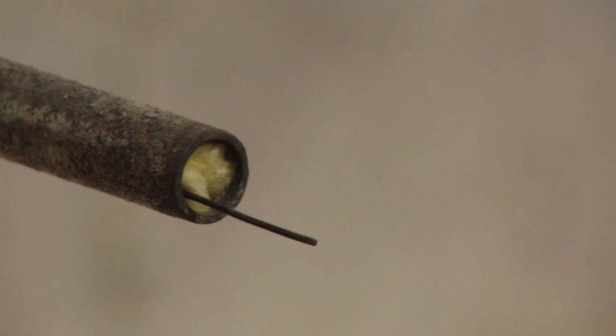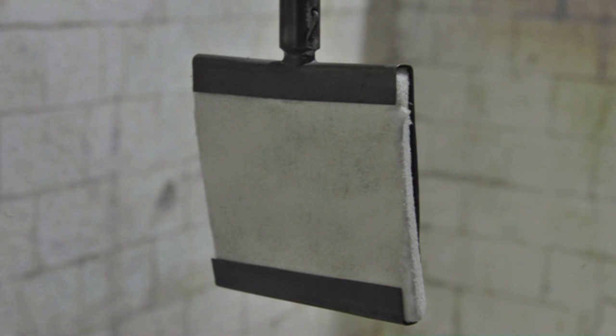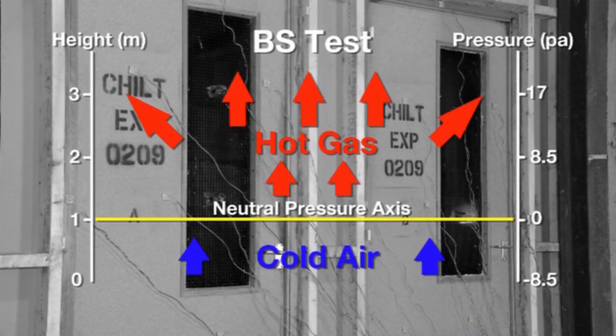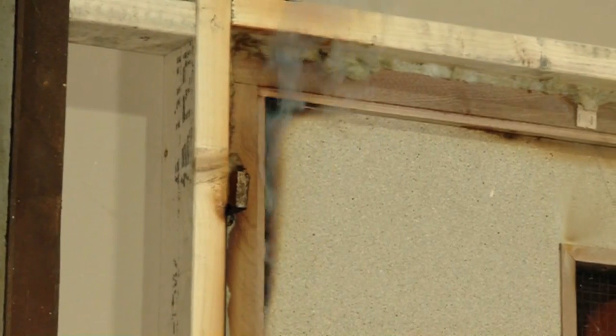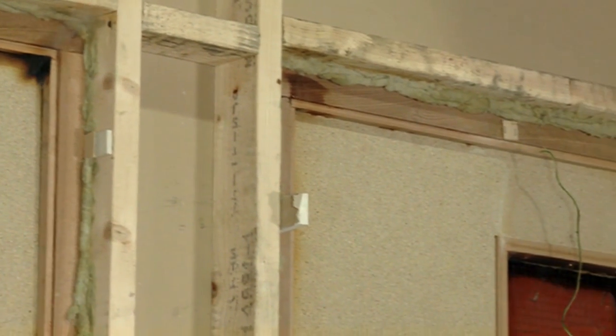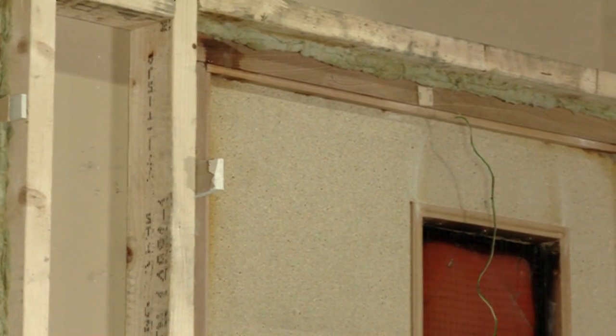The British BS standard specifies 1.5 mm probe thermocouples, whereas the European BS-EN standard specifies plate thermocouples. For the BS test, the neutral pressure point is set at 1000 mm above the threshold, whereas for the BS-EN test, the neutral pressure point is set at 500 mm. Both these differences can have significant effects on the performance of specimens, generally making the European test more challenging.